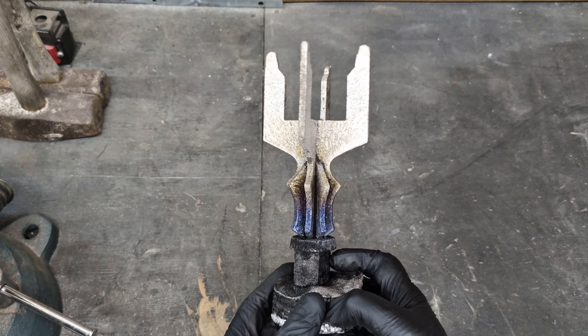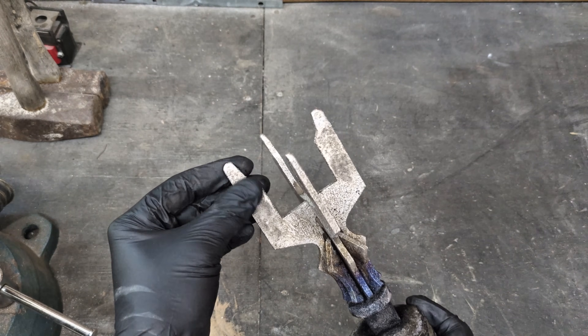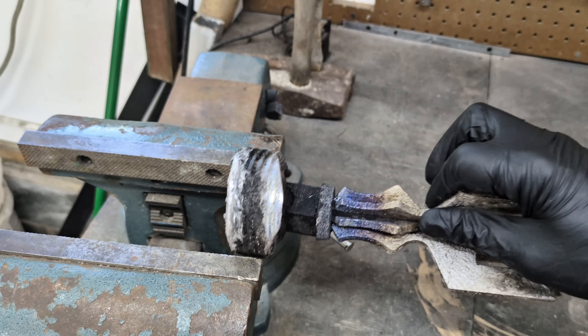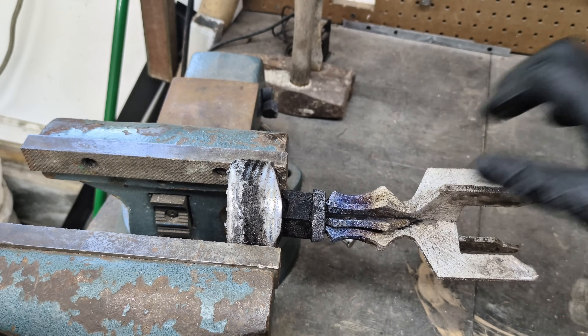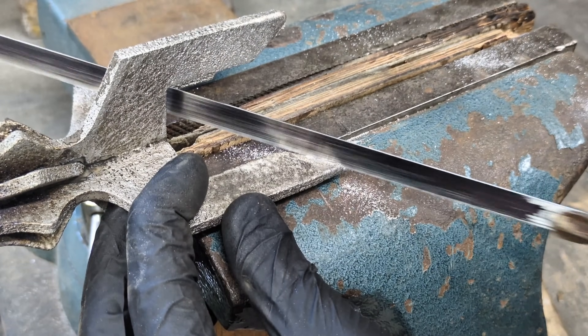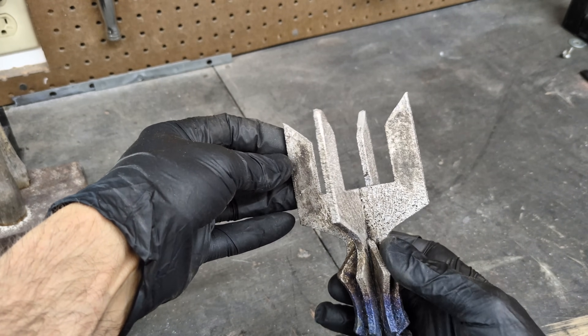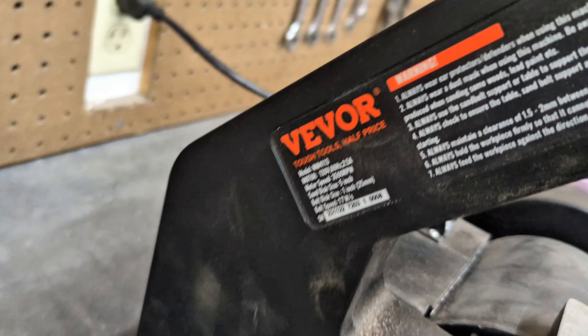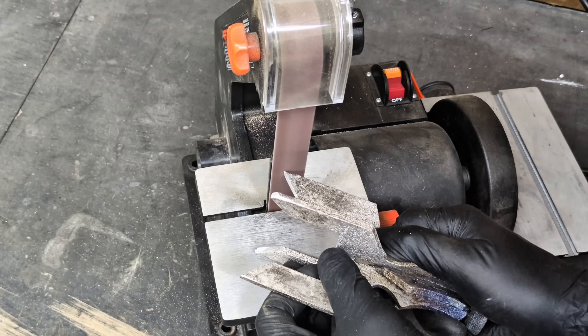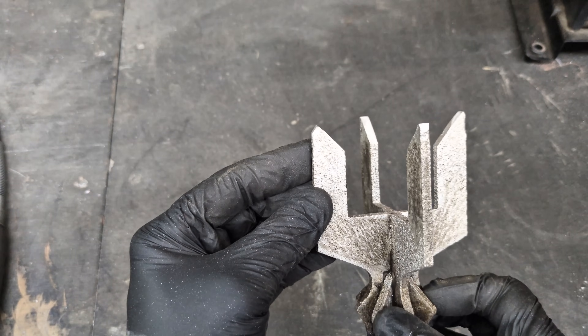When I pulled it out of the sand, this pattern did not completely fill out. If you remember from the beginning, those spikes were really long, and unfortunately the metal was not hot enough to make it all the way down to the very bottom. I did check the temperature before pouring and had the aluminum at 1800 degrees Fahrenheit, but that just wasn't enough. So because of the failed cast, I'm going to have to make some modifications to the spikes, cleaning them up using the VEVOR belt sander. And there we have it — almost perfectly uniform spikes, all four of them.